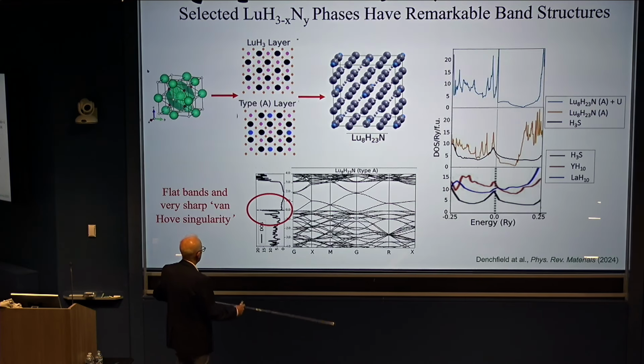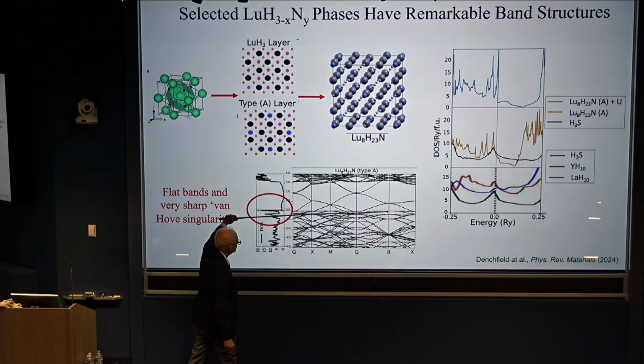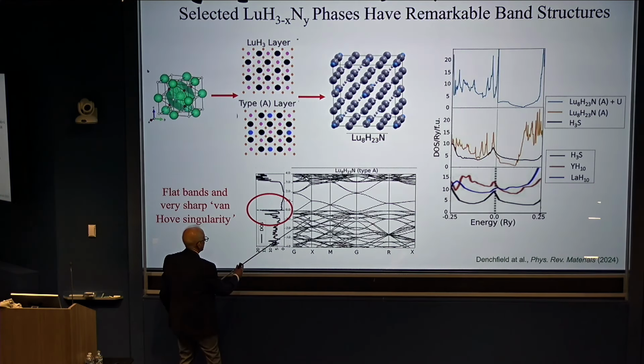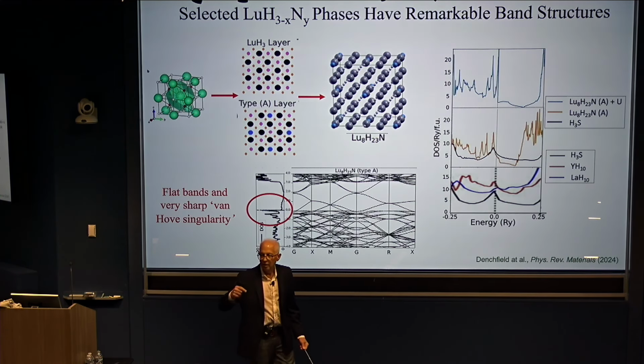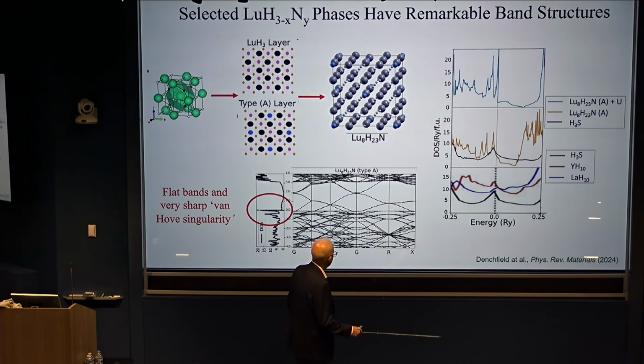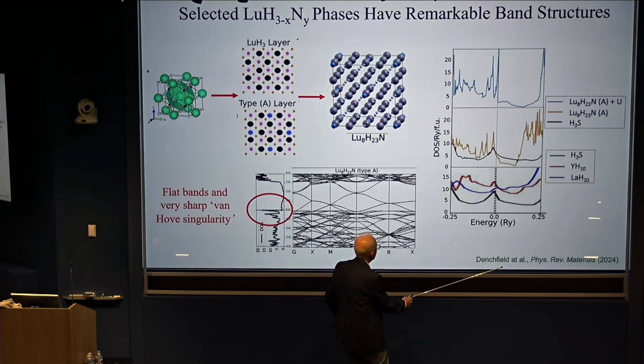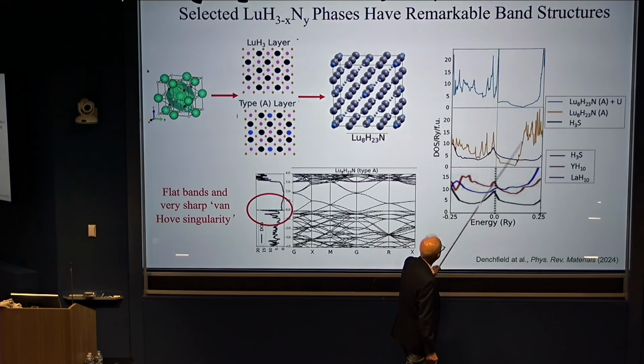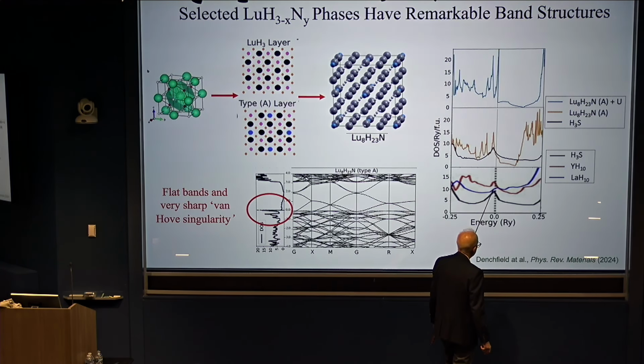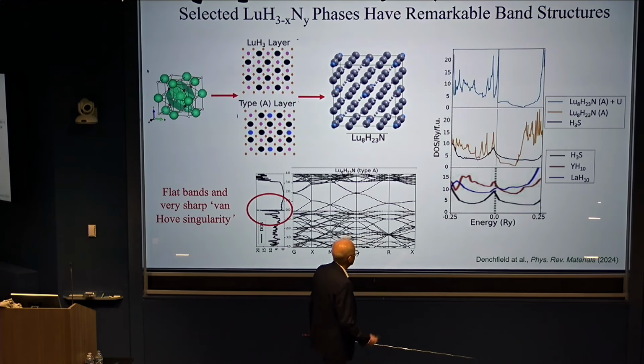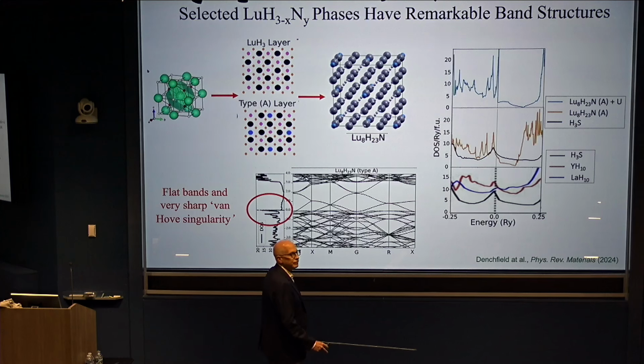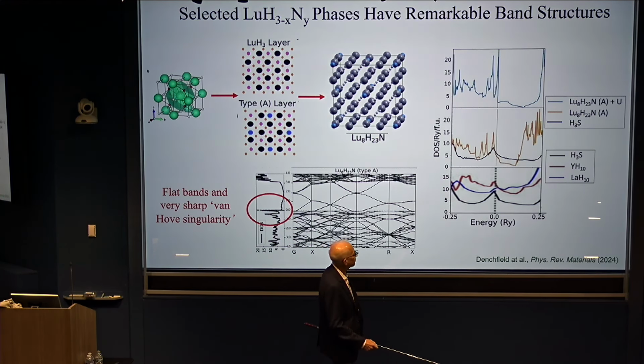This is somewhat technical, but what he found was certain layerings and certain compositions produce extremely flat bands right there at the top of the conduction band, and this gives rise to a very sharp peak here, which is also known as a Van Hove singularity, and it's a harbinger of superconductivity. We can't calculate the superconductivity because of the size of this unit cell, but it's a smoking gun for something interesting happening electronically. And what's also interesting is this is much, much sharper than what we have in these other materials, which we know are superconductors. This is very, very sharp in comparison to what we have with lanthanum hydride, yttrium hydride, and hydrogen sulfide. So if it's not superconductivity, it's still an extremely interesting electronic material.